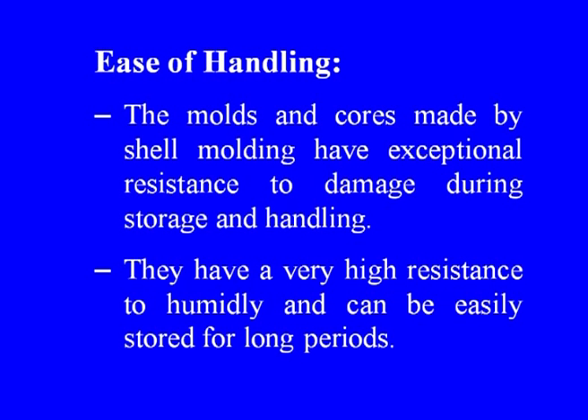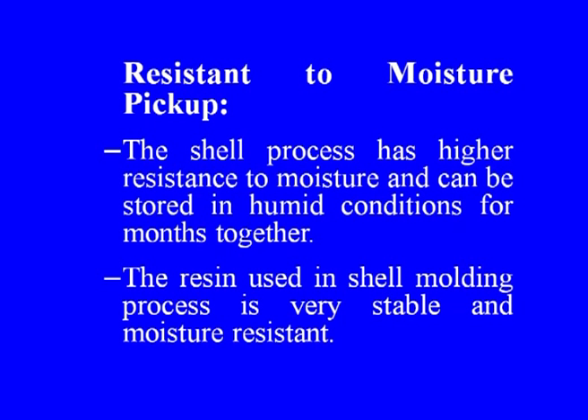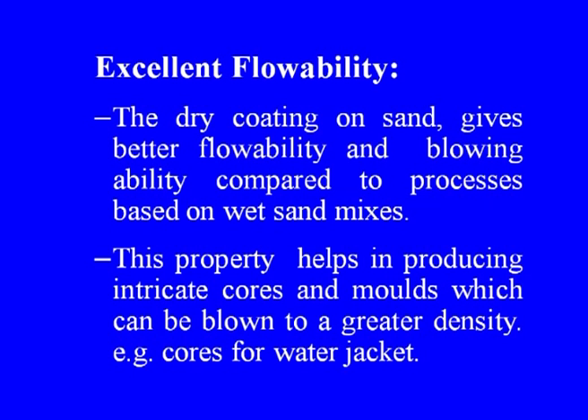Shell molds have very high resistance to humidity and can be stored for long periods. Resistance to moisture pick-up is another big advantage — the shell process has higher resistance to moisture and can be stored in humid conditions for months. The resin used is very stable and moisture resistant. Excellent flowability is another advantage: the dry coating on sand gives better flowability and blowing ability compared to wet sand mixes, helping in producing intricate cores and molds — for example, cores for a water jacket.